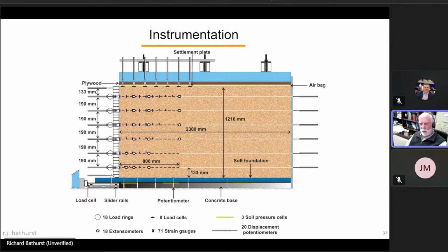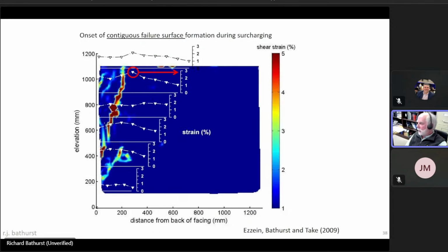And we could also test other things that were not convenient at full scale, including using rubber mats and foam pads to simulate more compliant foundations, and thereby see what influence these more compliant foundations, compared to a hard concrete base foundation, have on the performance of the reinforced fill and its deformations. Another advantage of these tests was that the box that I showed you had transparent sides, so we were able to use DIC monitoring to track the deformations in the reinforced fill.